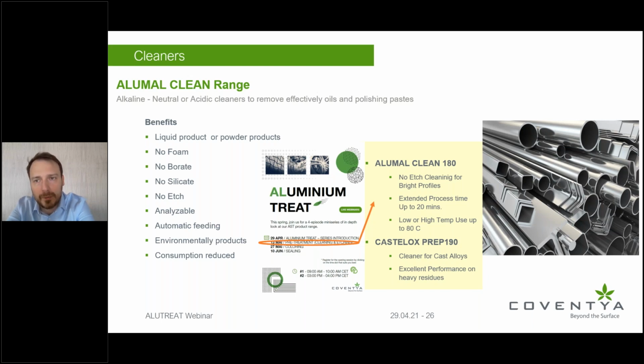But here you have one of our new cleaners, the ALUMAL CLEAN 180. This is specifically designed for bright profiles that are mechanically polished or chemically polished. This product is very good especially with automated lines, where the profiles need to spend a longer time than needed in this cleaner, where even extensive times like 15-20 minutes do not cause any etching or discoloration on the surface of the parts. And these are completely biodegradable and high temperature use allowed chemicals, where the cleaning action is very good compared to the other chemistries that are currently on the market.